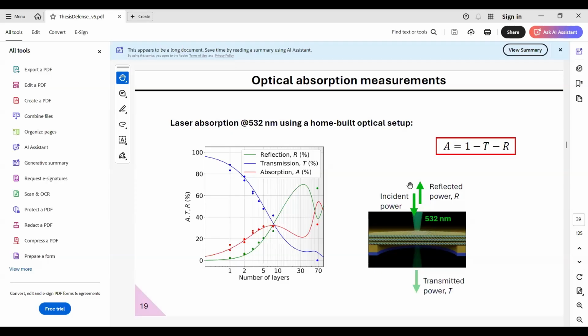So I was a bit puzzled about the large value of the absorbance. I was expecting something like 10% at the exciton resonance, like in the case of molybdenum diselenide. This one is off resonance, it's 532 nanometers, right? And the exciton resonance is at 785 for the monolayer. So we are off resonance, above the band gap. So I would expect a smaller absorption than at the exciton level. At the exciton resonance, I would expect around 10% for the single layer. I was puzzled that this is also like that.